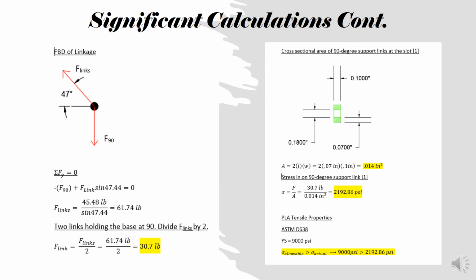So from there, we knew the highest stress was going to be in the slotted portion of that linkage. We calculated the area of that section, and then we used stress equals force over area, and we got 2,190 pounds per square inch roughly. We then compared it to the PLA tensile properties, using the ASTM D638. That value was 9,000 psi for its yield strength. So we can see that we are well under the yield strength for that PLA.